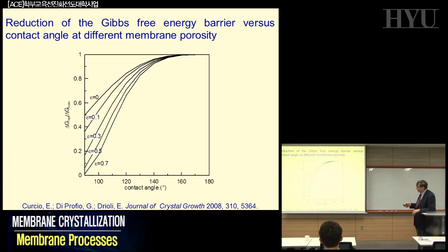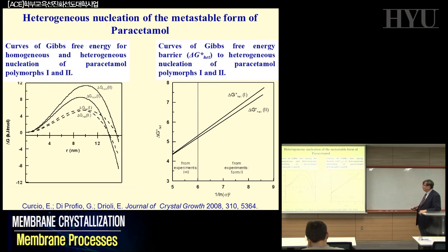So all this analysis of the Zeldovich can be easily transferred to this delta G heterogeneous and delta G homogeneous for a microporous hydrophobic membrane, with a quite interesting agreement, introducing the different parameters characterizing membranes: porosity, surface porosity, etc. This also was a quite interesting effect.